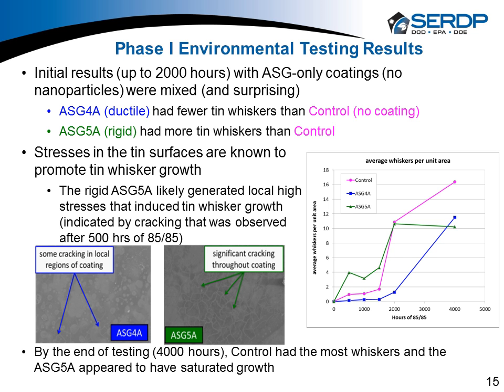And what we found out real early, and I hope it shows up in your PowerPoints, but on the right here, this is ASG5. And you can see it's crazed. It has a lot of cracks in it. And what we found is the ASG5 was too stiff. It was causing cracking. The cracking was then generating stress into the bright acid tin coating underneath. And the whiskers just thought that was great. They just grew like crazy, and especially early on, if you look at the graph.